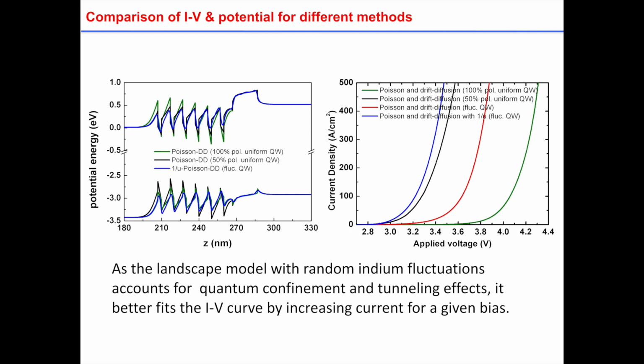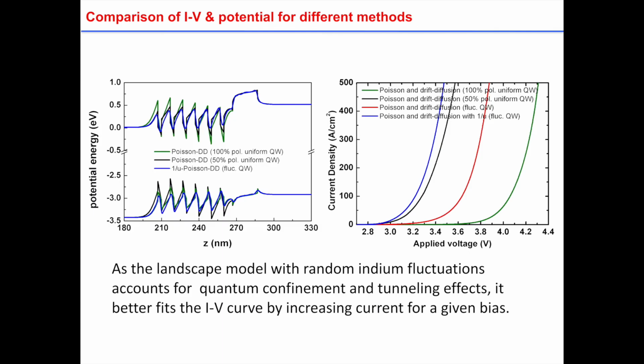This is extremely important because it is at the origin of explaining why the turn-on voltage of a blue LED is about 3 volts. When you do the simple calculations of every commercial 1D simulator that you could buy today, you would find a voltage larger by 1 volt.